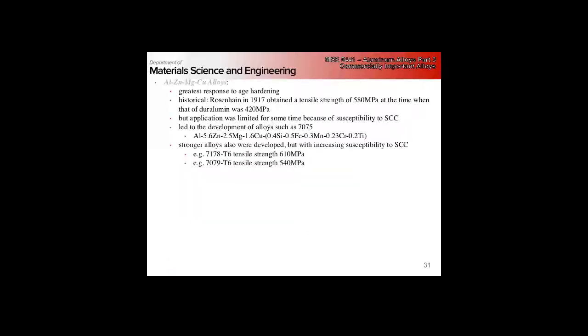So the ternaries are sort of these medium strength alloys. Once we go into aluminum, zinc, mag, copper, this becomes quite complicated, and each alloy responds sort of differently. But this system gives us, out of all the age hardening systems, the greatest response - the greatest delta from the quenched to the aged condition. These were found around the same time as duralumin. Duralumin was what, 1913? This is 1917, right?